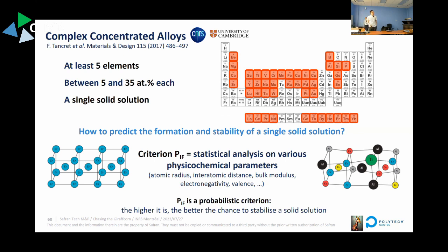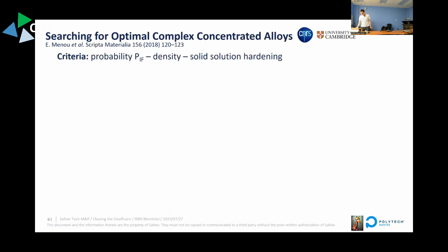Complex concentrated alloys. Just two examples. The idea was to find alloys with a single solid solution. That was our goal, because that was the original definition of a high entropy alloy. Don't ask me why we would want to find a single solid solution. That was a bit of a hobby at the time. And the idea is that we had a probability criterion that is well described in this paper, if you're interested. That tells you, based on composition, the probability of finding a single solid solution. And so we applied that together with two other models: a rule of mixture model for density, very simple, and we had another for solid solution hardening.